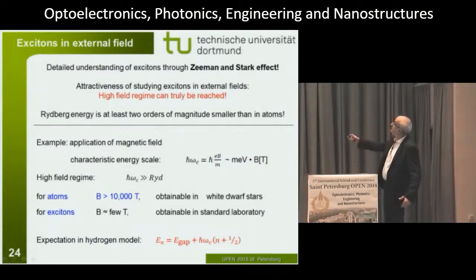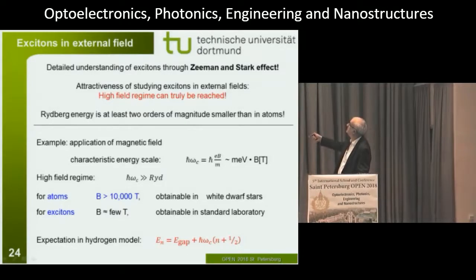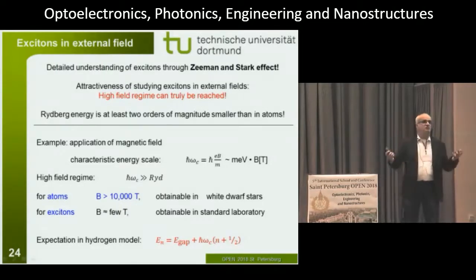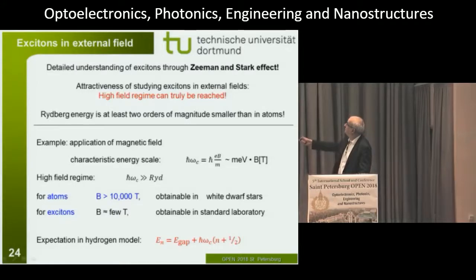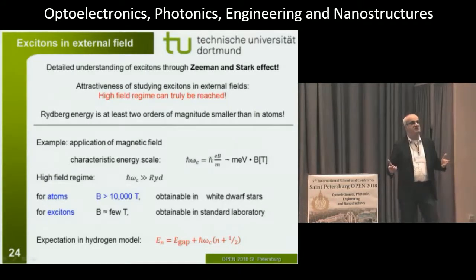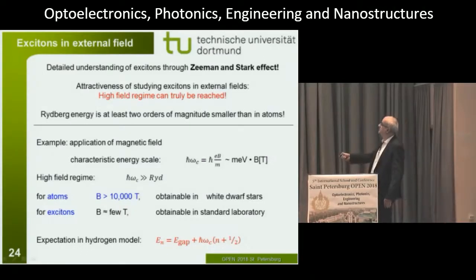Well, the reason is again that we can truly enter the high field regime, because our Rydberg energy is much, much smaller. For example, if you want to apply a magnetic field, the characteristic energy scale is obviously the cyclotron energy, so h bar times electric charge times B, the magnetic field strength, divided by the mass. And typically for semiconductors, this gives you a millielectron volt or so times the magnetic field strength. So if you want to enter the high field regime, which is defined by the fact that the cyclotron energy is much larger than the Rydberg energy, for atoms you need to apply 10,000 Tesla, which you find in white dwarf stars, but not really on Earth, while in our case we just need to apply a few Tesla. And this is of course standard today.